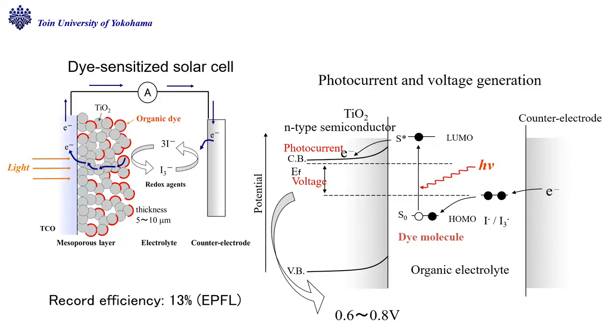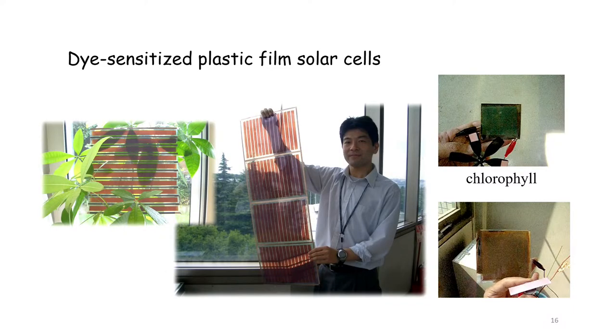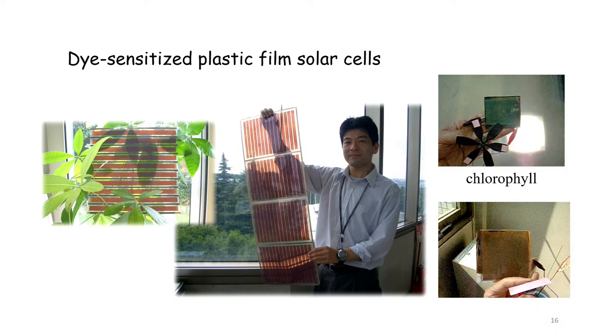So this is the mechanism of dye-sensitized solar cell invented by Professor Gretzel. So this is a mesoporous TiO2 electrode. This is iodine redox agent. So this is a mechanism of how the voltage and photocurrent are generated by photo-exciting the dye monolayer adsorbed on the surface. So in university, I started work to make a lightweight, flexible, plastic-based dye-sensitized solar cell for a practical application. So, interestingly, this is a chlorophyll sensitized electrode, plastic electrode.